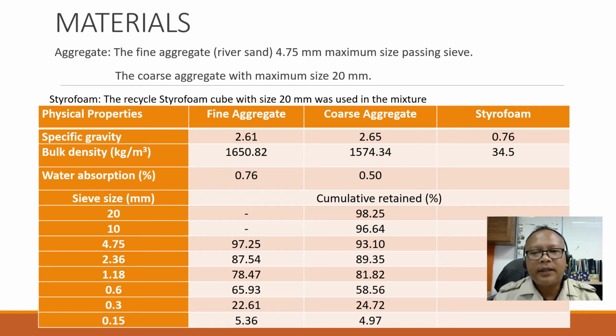For the bulk density, fine aggregate is 1,650.82 kilogram per meter cube, coarse aggregate 1,574.34 kilogram per meter cube, and styrofoam is 34.5 kilogram per meter cube. For the water absorption, fine aggregate is 0.76%, coarse aggregate 0.50%.